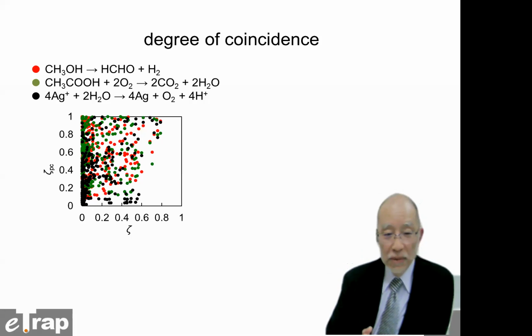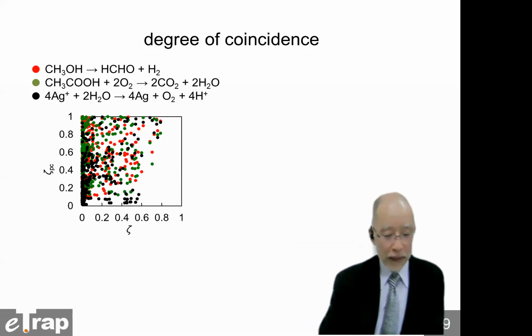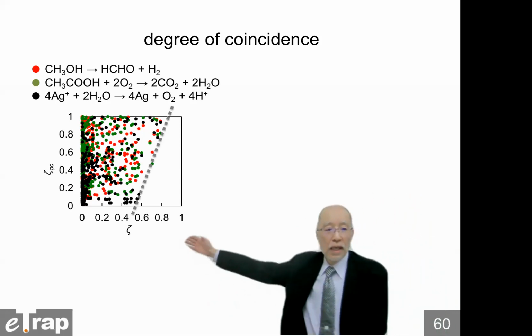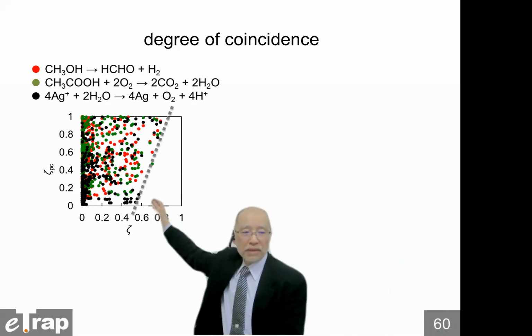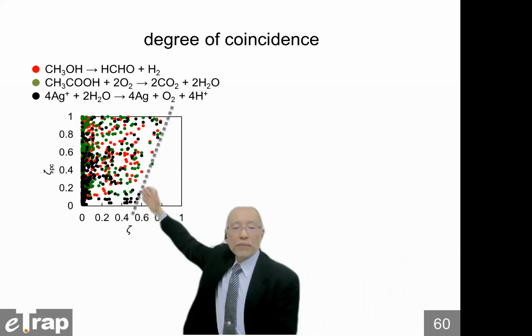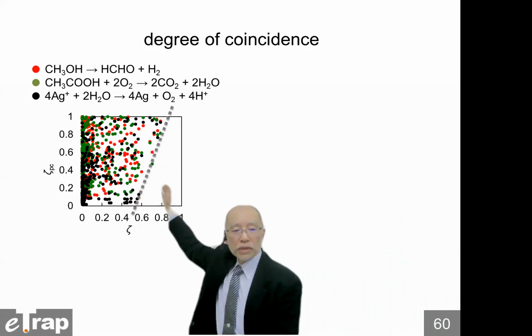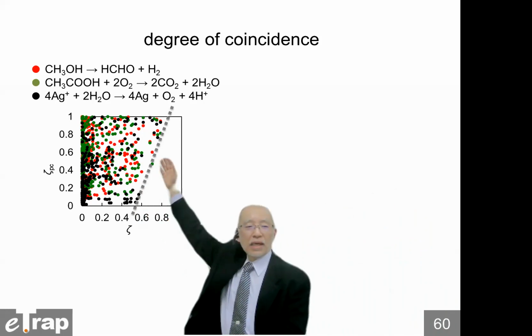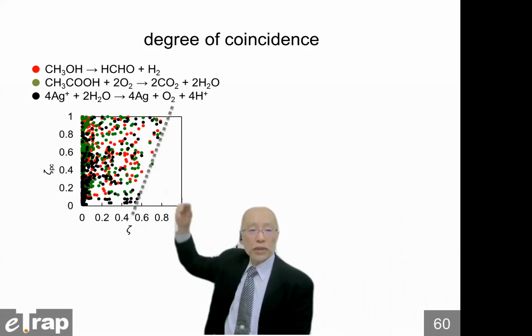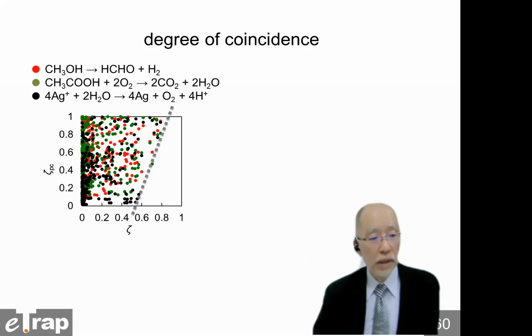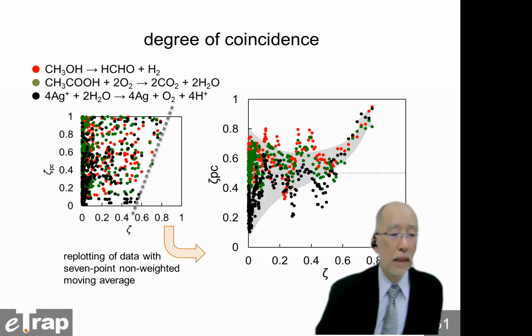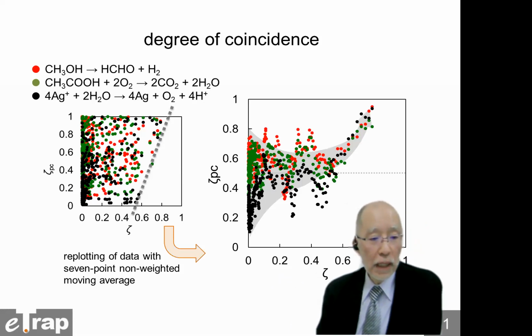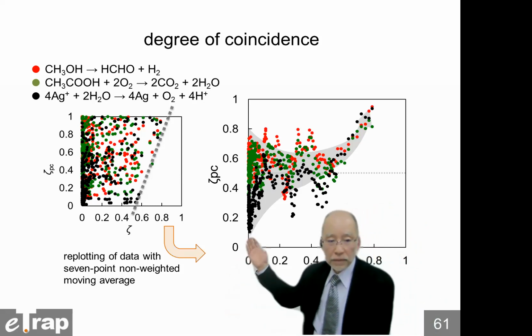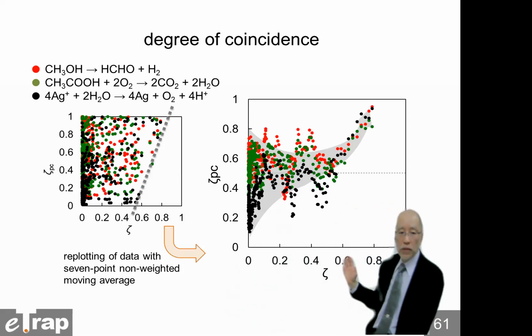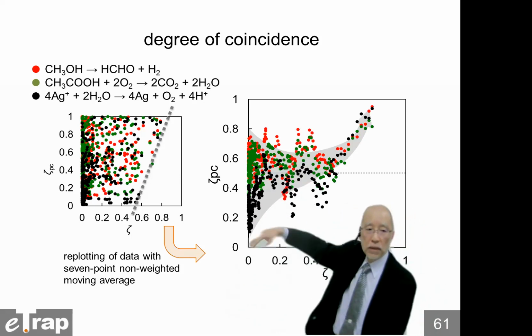And there is almost no relation, just scattered. But here is a line. So pairs with a high degree of coincidence, higher than 0.6, don't give a lower degree of coincidence of photocatalytic activity. That is, every time, a high degree of coincidence of photocatalytic activity. To make this tendency clear, I used a 7-point non-weighted moving average, which is one of the averaging methods for such scattered results. And again, if the degree of coincidence is lower than 0.6, it is scattered so much.